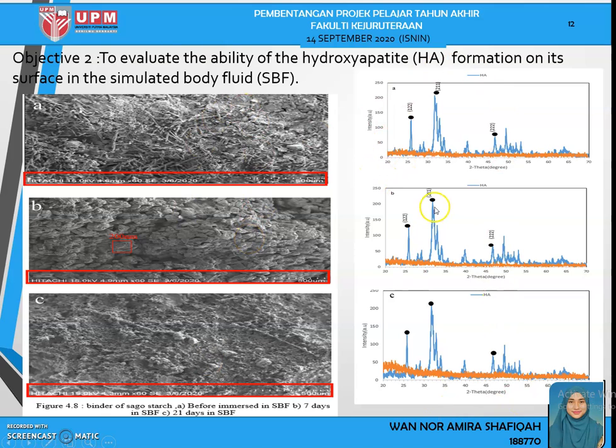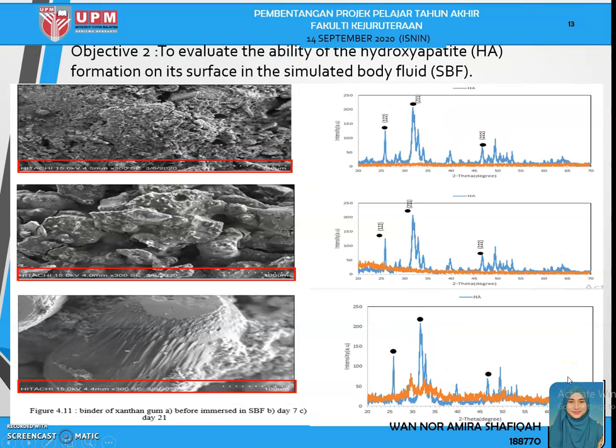So this is the XRD analysis to know the crystallinity of the sample. If we can see here, when the time increases, the crystallinity also increases. For the xanthan gum, based on their figure, it can be observed that the crystal formation appears on the surface of the tablet when it is immersed for 7 and 21 days.